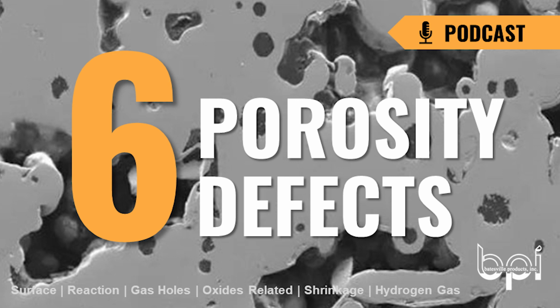On a sand core, you have a reaction with the core that's going to show up on the internal surfaces of the casting. So as Ernie said, it's surface related. If you were to take a cross section through, you're only going to see it very close to the surface. It's not going to be internal. Typically, it's a finite type of porosity. It doesn't leak or anything. It's just what you see is what you have.